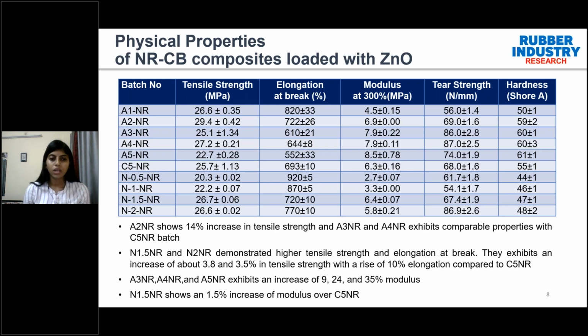So A3NR, A4NR, and A5NR actually increased the modulus by about 9, 24, and 35%. So in a nutshell, we can say that the modulus, tensile strength, and elongation were better in all these active zinc oxide loaded and nano zinc oxide loaded compounds.